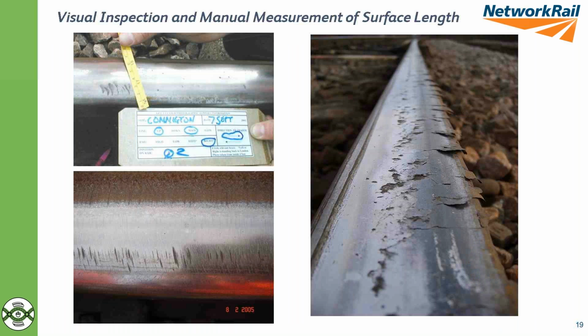The next slide is just an example one I put up. Traditionally, we've looked at using visual inspection to try and locate RCF, focused primarily in curves, focused often on the high rail, but it doesn't always occur in those locations. We often get other sorts of damage.